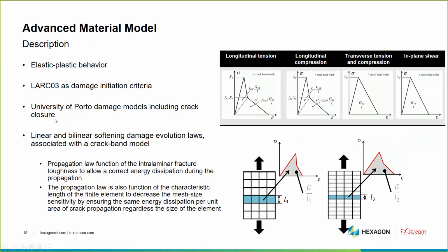So the way those propagation laws are defined, they have a specific shape. They are linear and bilinear softening damage evolution laws. So this is the typical shape that we use, bilinear and linear, depending on the loading condition. And those evolution laws are associated with a crack band model. So here, the propagation law is a function of a physical parameter.